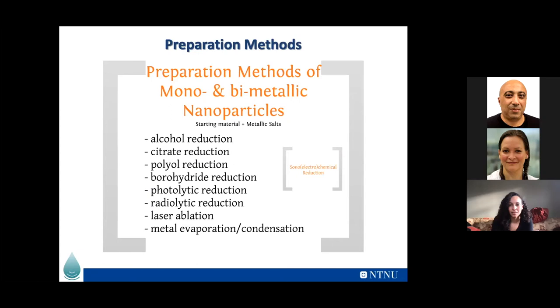So for chemists, to prepare your catalyst, you have the chemical route. You use alcohol reduction, citrate reduction, polyol reduction, and sodium borohydride reduction, which has been used quite a lot. And you also move into something more physics-based, such as photolytic reduction, radiolytic reduction, laser ablation, and other types of routes. What I want to present is that we can get those nanoparticles in situ by using sound, or ultrasound, or in fact a combination of sound and electrons.